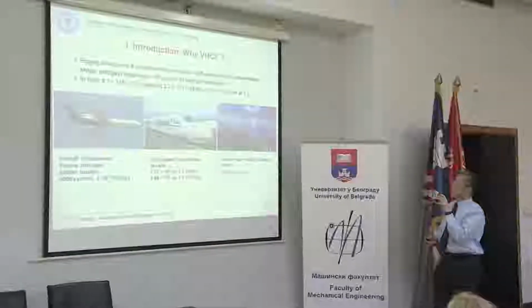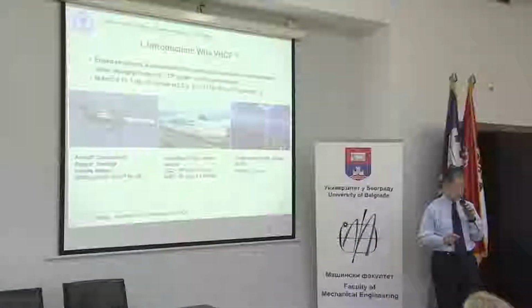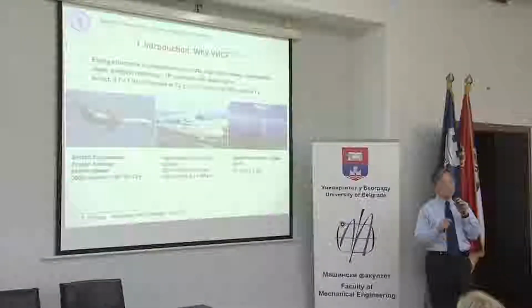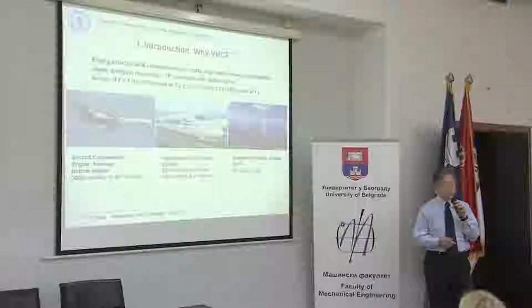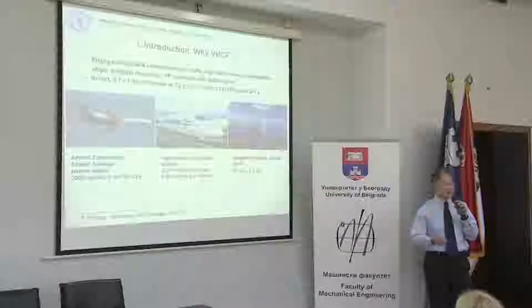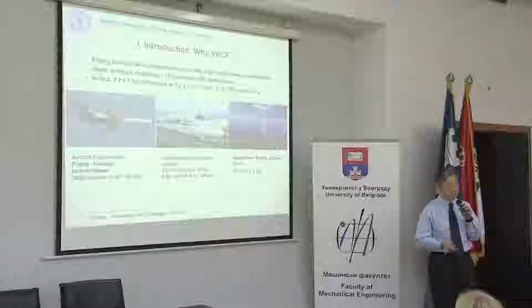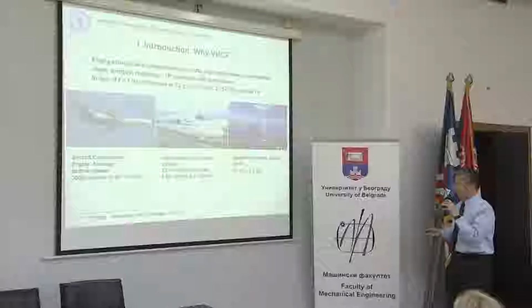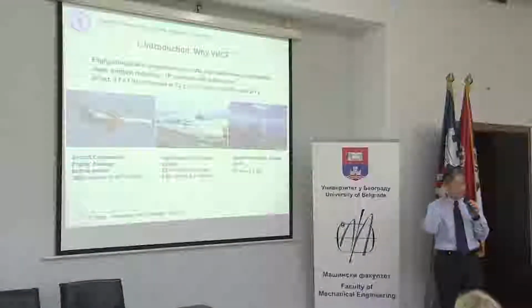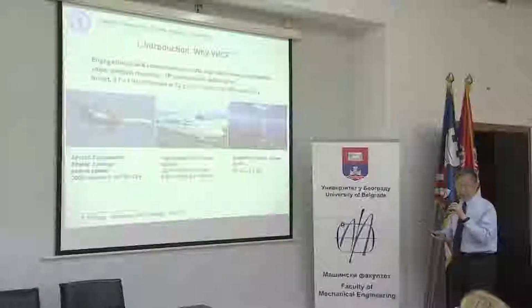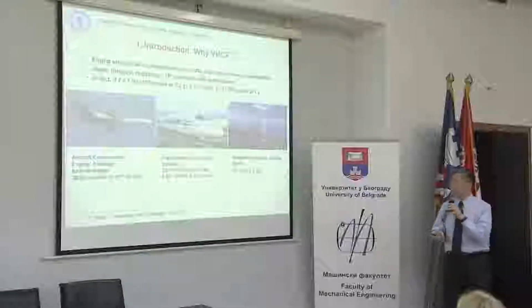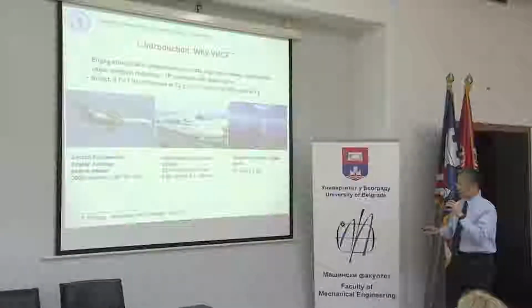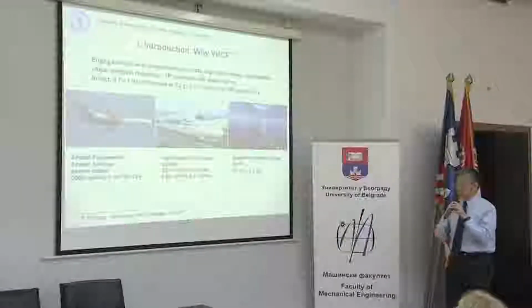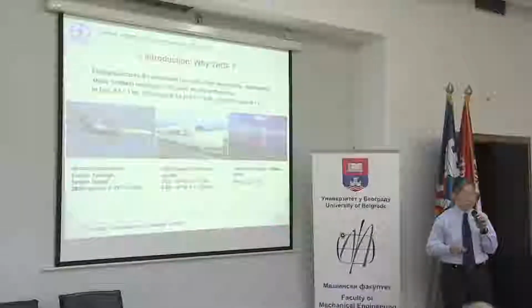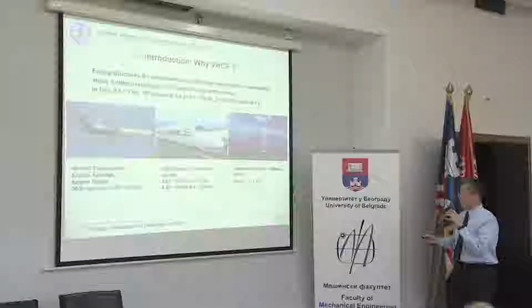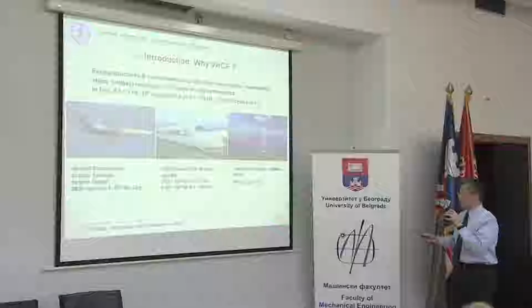And we always say very high cycle fatigue is a very important area to be investigated, because many engineering structures require a large number of cycles of performance, always beyond 100 million cycles. And we may have an idea that such very high cycles are very easy to reach. For example, if the frequency is 1 Hertz, just a little bit more than 3 years will reach 100 million cycles. And if the frequency is 10 Hertz, just 1 year will be more than 300 million cycles.